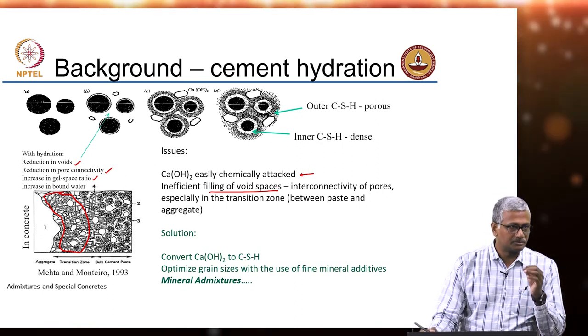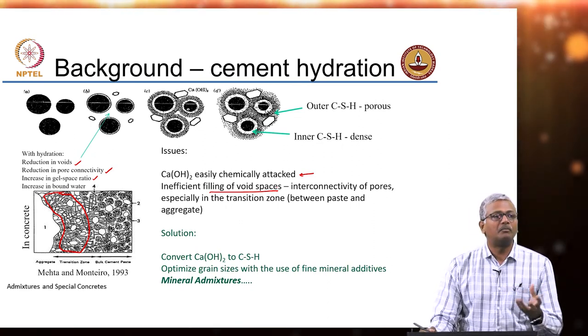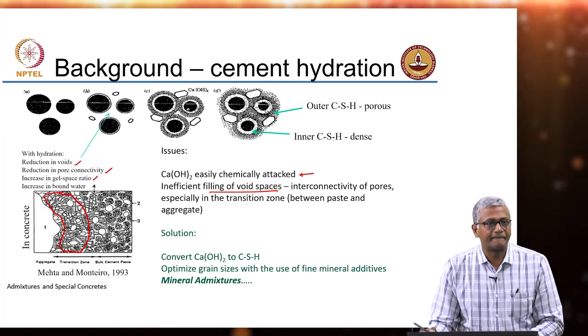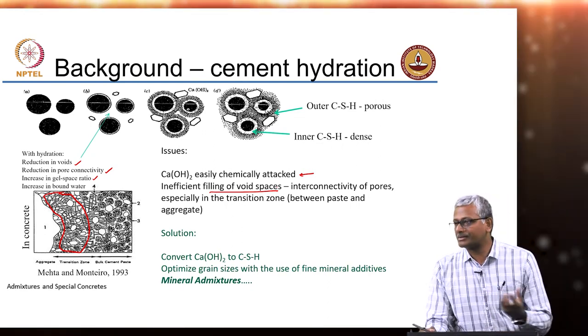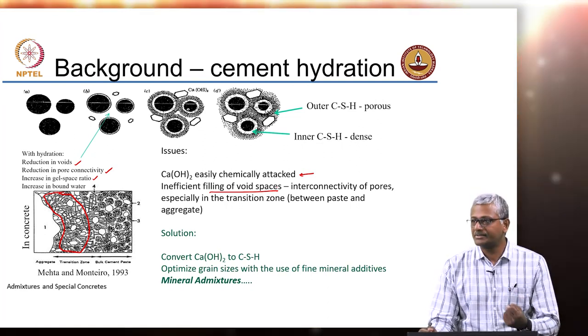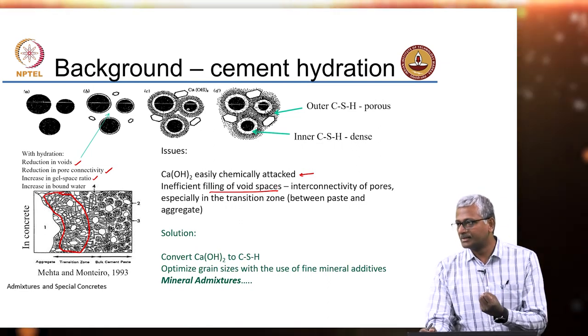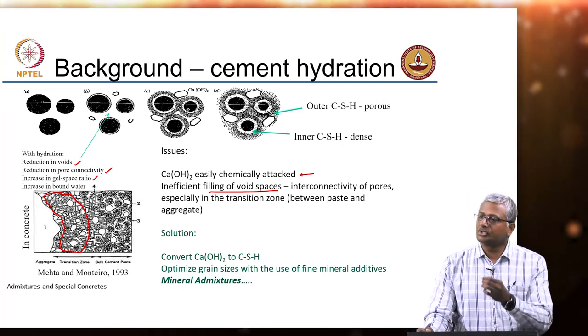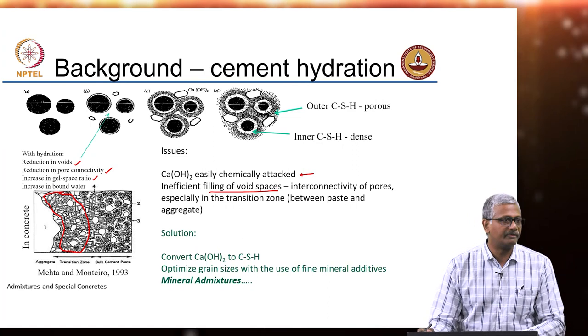The key to ensuring durable concrete is to ensure that pore spaces have been sufficiently filled up. The compound in cement hydration products most efficient at filling pore spaces is CSH — because of its irregular, sheet-like structure and very high surface area, it provides extremely dense packing. Calcium hydroxide and ettringite, being well-defined crystals, leave a lot of void spaces unless they pack very tightly. Conversion of calcium hydroxide to CSH therefore leads to more efficient filling of available pore space.